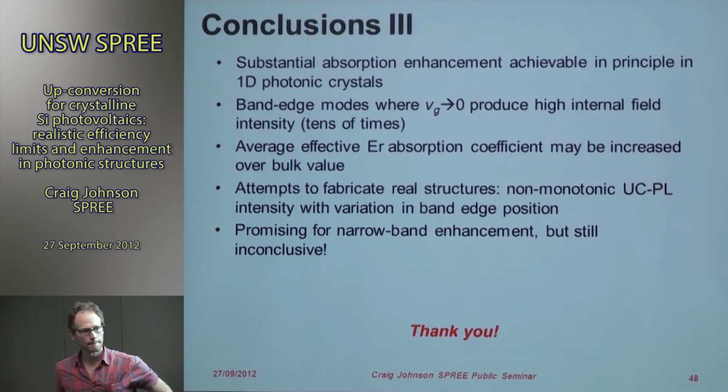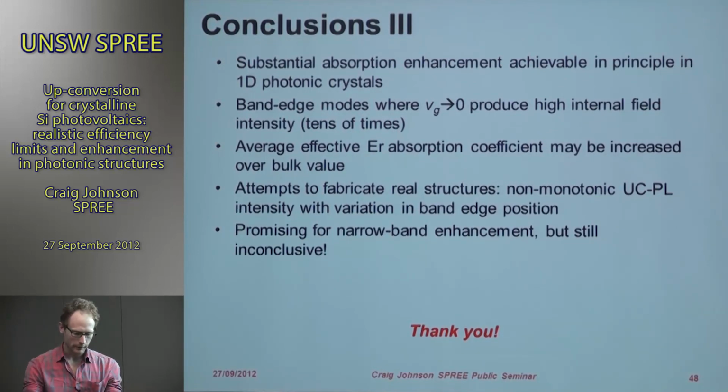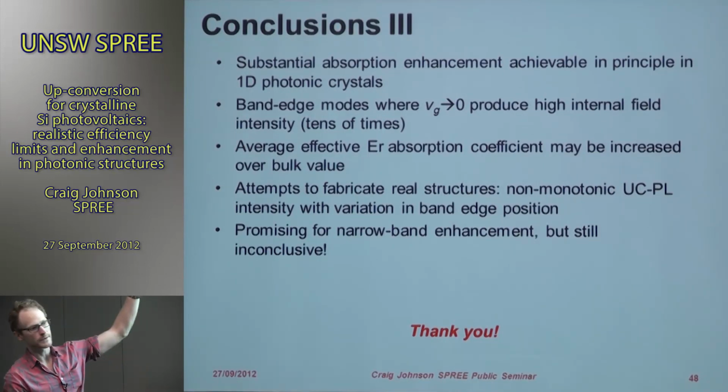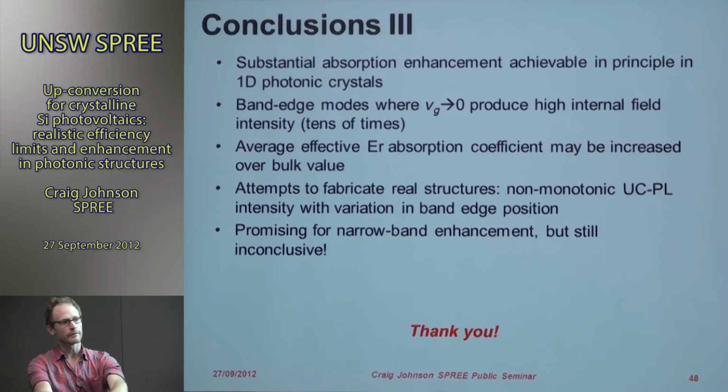Actually, I've got one about your porous silicon Bragg reflector. So how did you actually get the layers in? It's an interesting process because you start with crystalline silicon, and as you etch the top layer, so the top layer that was in that image was the first layer that was etched. As you etch, you provide a pathway for HF to enter the structure, and then it etches selectively at the interface.